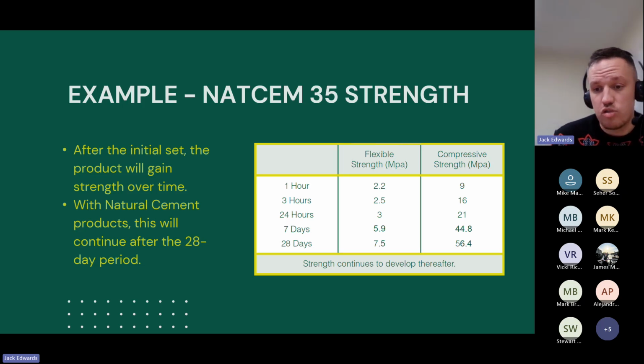You can see the strengths that are achievable. Obviously, these are all based on 20 degrees lab conditions. You'll get some slight differentiation on site, but the strength gain is very, very similar, even at a lower temperature, if you're using warm water to accelerate that initial setting time. Another unique property of a natural cement is the fact that even after the 28-day period,